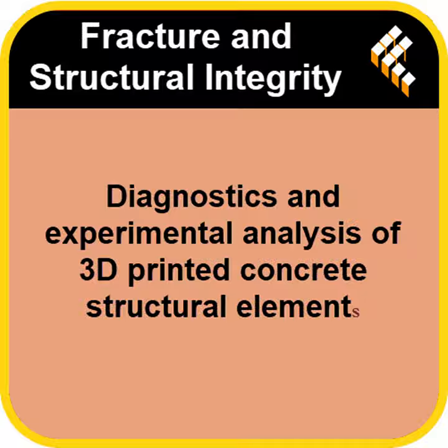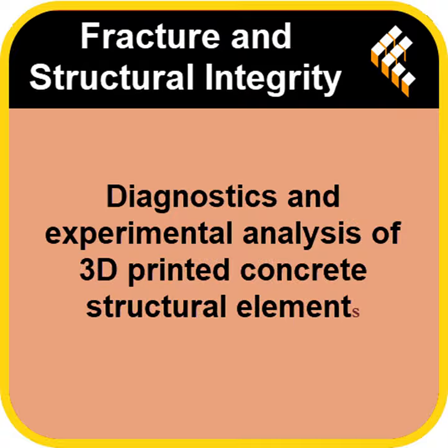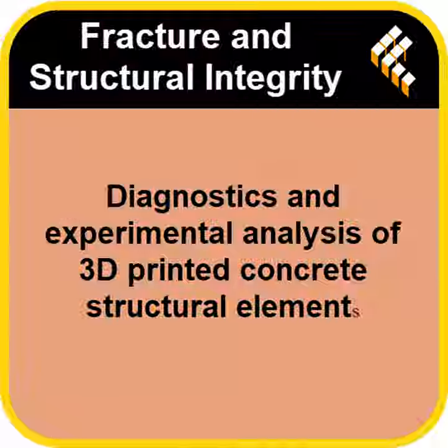So which property was the weakest link? Flexural tensile strength, without a doubt. That's its resistance to being pulled apart while bending. Okay. When they tested it parallel to the layers, the mean strength was about 1.96 megapascals. But when they tested it perpendicularly, trying to pull those layers apart, where did it drop to? The mean dropped to 1.27 MPa. That's a reduction of over 35%, just based on the direction of the load. I mean, traditional safety factors in engineering just don't account for that kind of swing. And that's just the average. The variability was extreme. The lowest value they recorded for perpendicular strength was a shocking 0.56 MPa. Wait, 0.56?